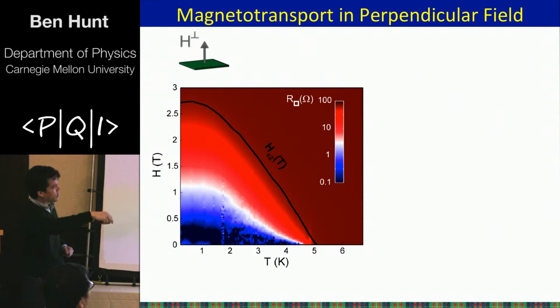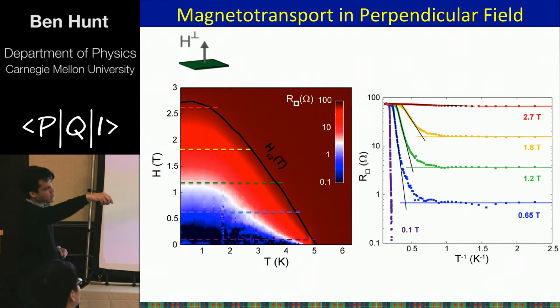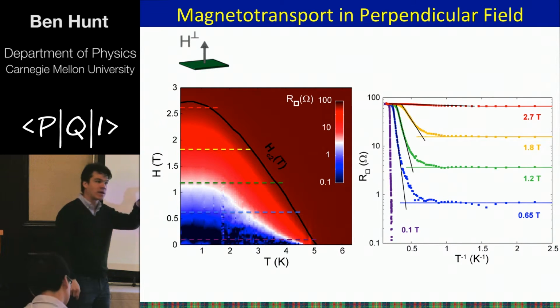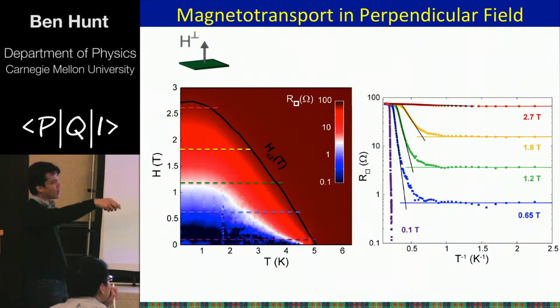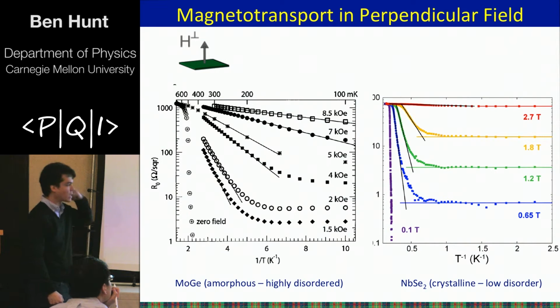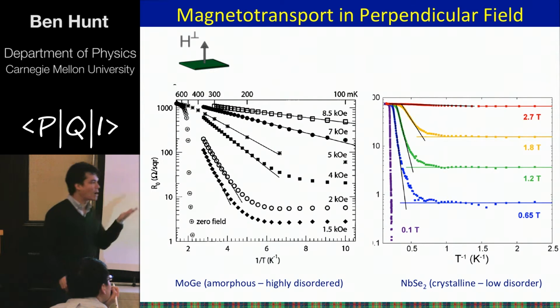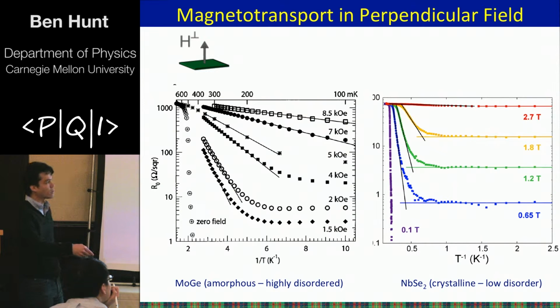And if you take some line cuts along here, this is now on 1/T versus log R axes to bring out the Arrhenius behavior. But what you can see is that, in fact, as a function of magnetic field, the resistance is not 0 down here, but it saturates to a finite value as we go to low temperature on the right-hand side, okay? So if we compare back with this amorphous molybdenum germanium film, you can see that the data look very similar, right? There's this behavior where the resistance at low temperature increases as we increase the magnetic field, okay? So the main difference I wanted to point out again is that these were in amorphous films, and this re-observation of this metallic state is in this very low disorder crystalline superconductor that we produced, okay?